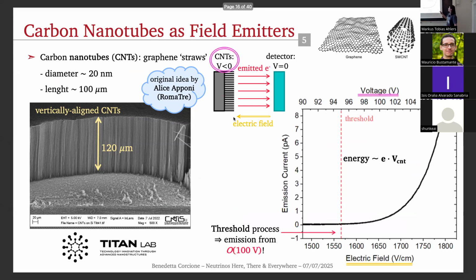Now, a typical trend of the field emission current is exponential with respect to the electric field, which in this case is equivalent to the voltage of the nanotubes. And this is a threshold process. In our sample, we just need hundreds of volts to have electrons. But we also have to take into account the fact that the kinetic energy of these electrons once they reach the transition edge sensors is proportional to the voltage we give to the nanotubes. So we have a little bit of constraints here.